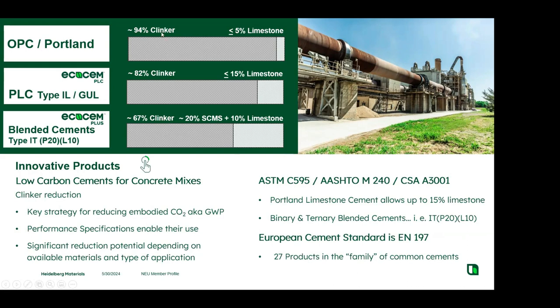Portland cement has a clinker factor of 94, 95%. Portland limestone cement has a reduction of about 10% below that. This is a 12% reduction in this example here. So EcoCem PLC will have up to 15% limestone, which helps us reduce our clinker factor. And then blended cements, which have not only limestone, but also in most cases, a supplementary cementitious material such as slag or ash or some of these other materials incorporated in that. We're going to get this clinker factor down much further. We have slag cements where that clinker factor is down well below around 50% or a little bit below 50%. So these are innovations that we're able to use.